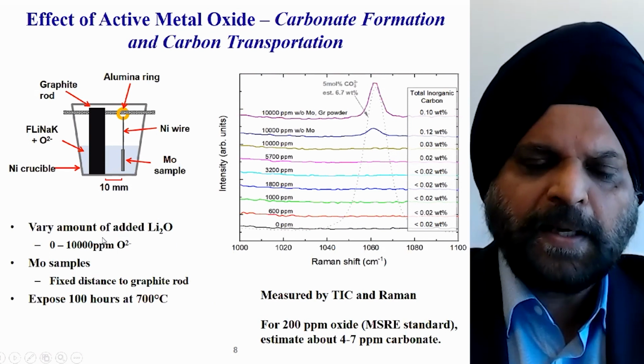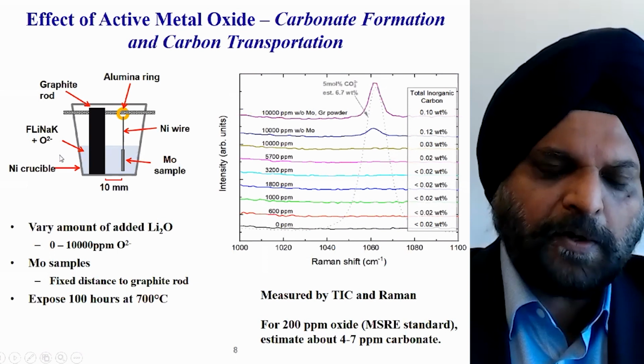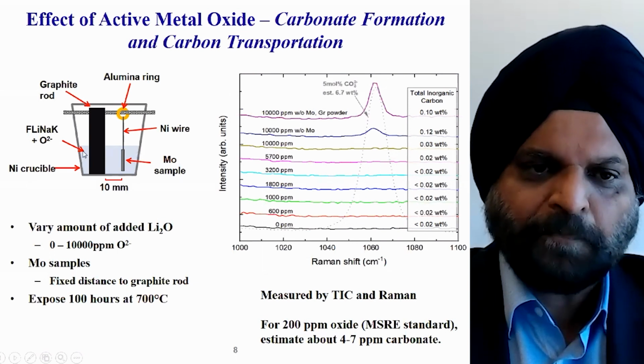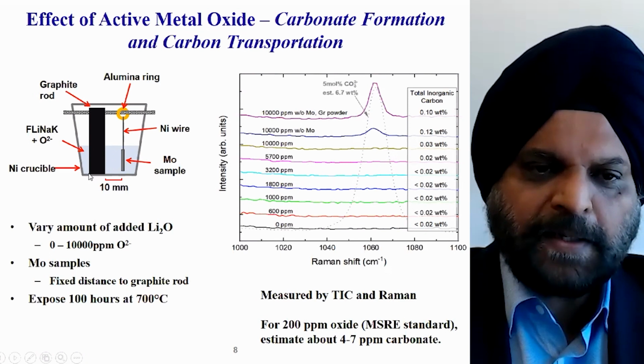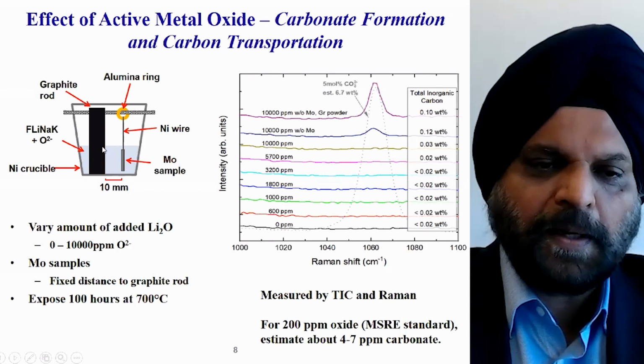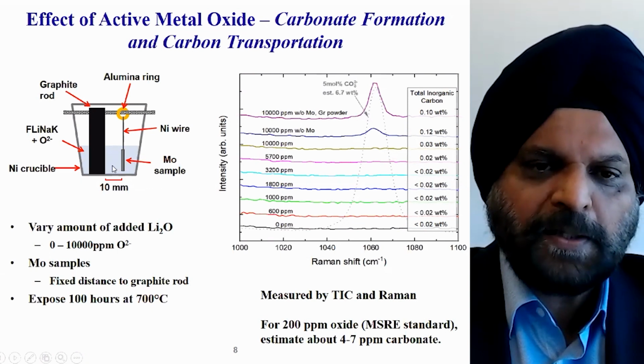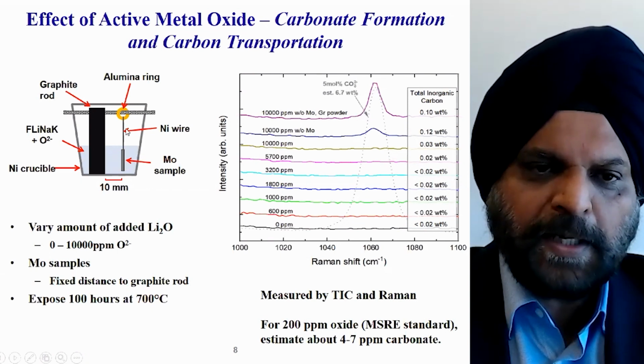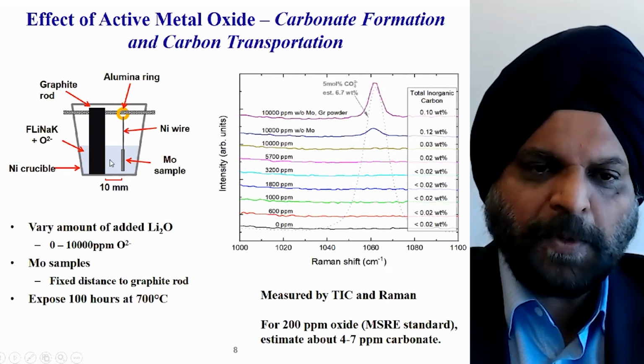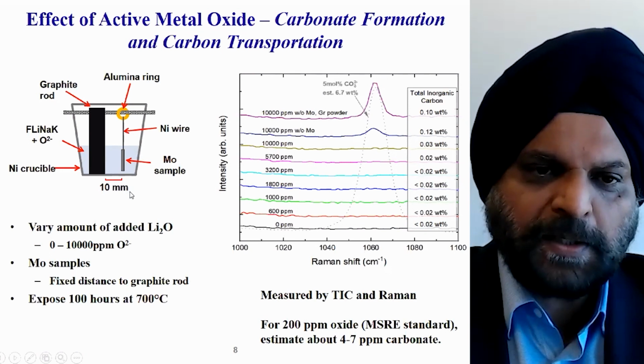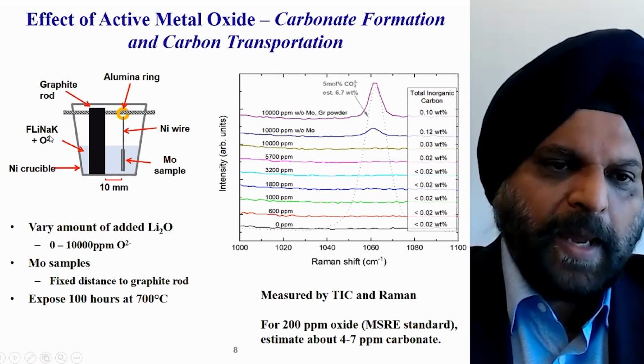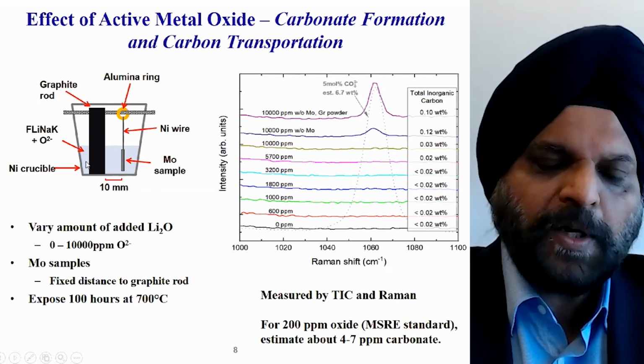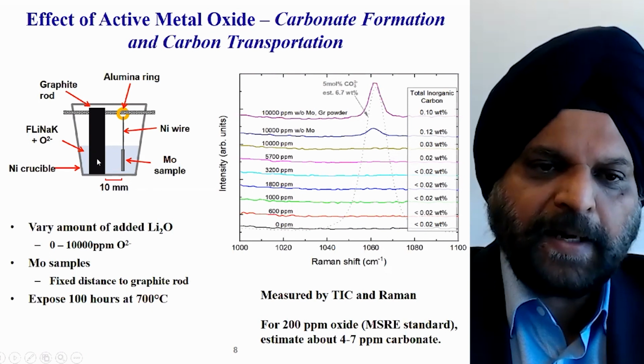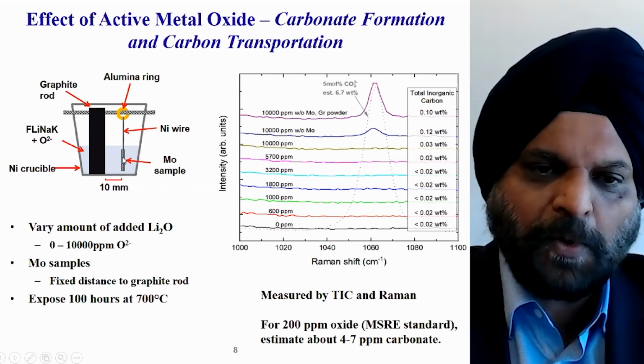And we found that as you keep on increasing the amount of oxide in the FLiNaK, so in this case we didn't add carbonate because we wanted to see if carbon can be transported from graphite to a molybdenum sample, which are totally isolated electrically. They are farther apart, about 10 millimeters apart from each other in this crucible. So we were adding oxide so that carbonate could form on the graphite surface and get transferred to the metal surface. In this case, the metal was molybdenum because it forms molybdenum carbide.